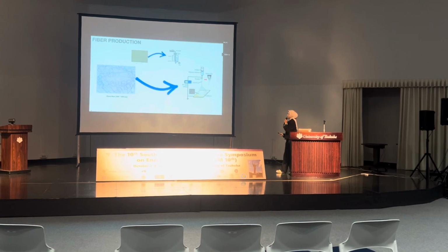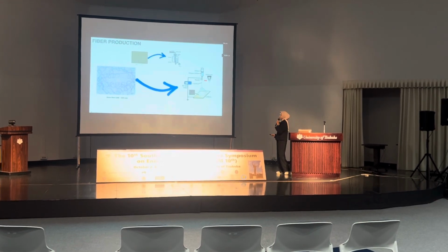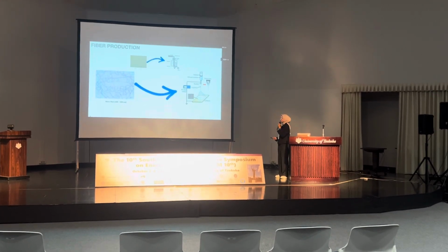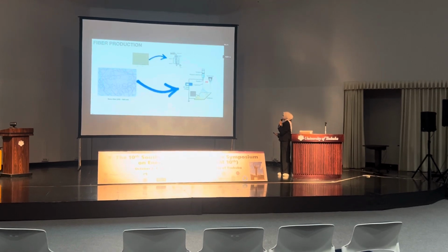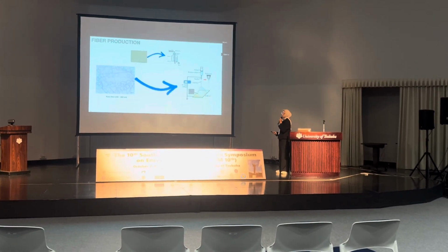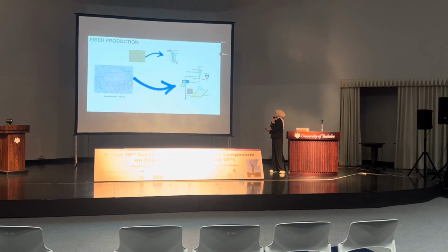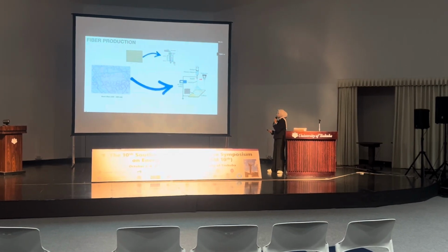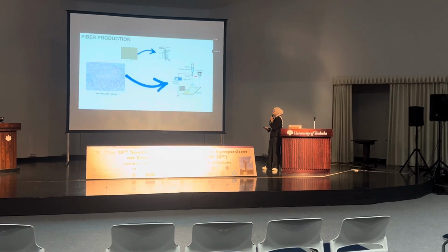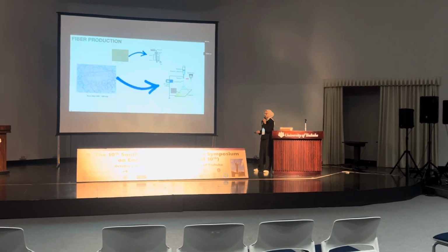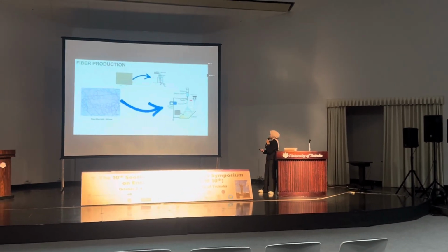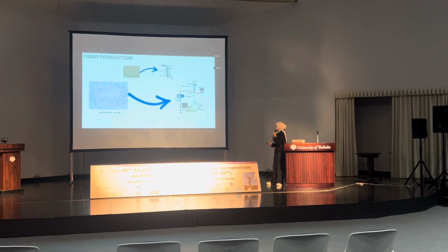While the nanofiber is produced by the electrospinning technique, where the machine usually consists of a syringe, needle, collector, and applying a high voltage. When the polymer solution is applied into the syringe, due to the high voltage applied to the system, the nanofiber will be ejected from the tip of the needle and deposited on the collector.